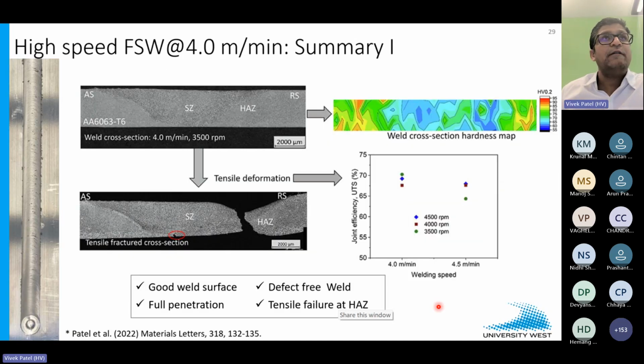We tried, and after optimizations, we found that 4 meters per minute welding speed gives a reasonably good joint, and that qualifies as per the ISO standard of friction stir welding.